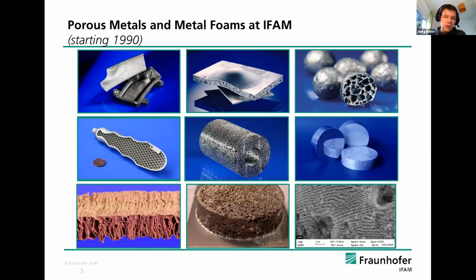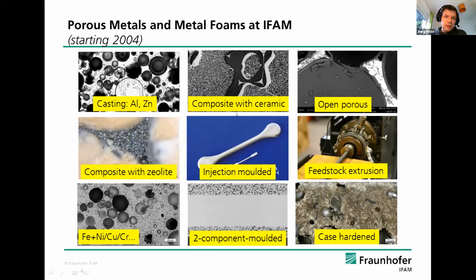Also other sintered open porous foams, open porous magnesium foam in the middle. And we recently started also to look at nano porous metals produced by means of de-alloying. And coming to the syntactic foams, we started a bit later in 2004. I was still in the casting department, so we started with casting production of syntactic foams with aluminum and zinc. We also combined it with other kinds of foams. In the middle top, you see one example of a syntactic foam combined with a ceramic foam.